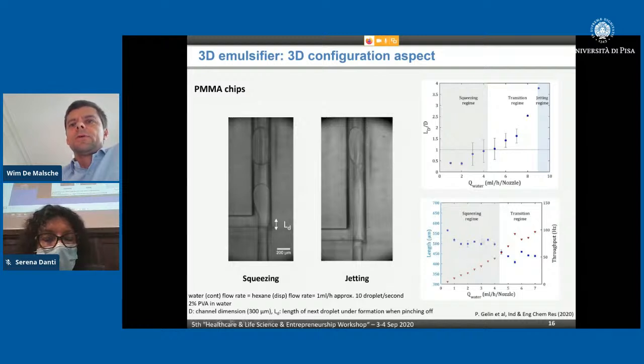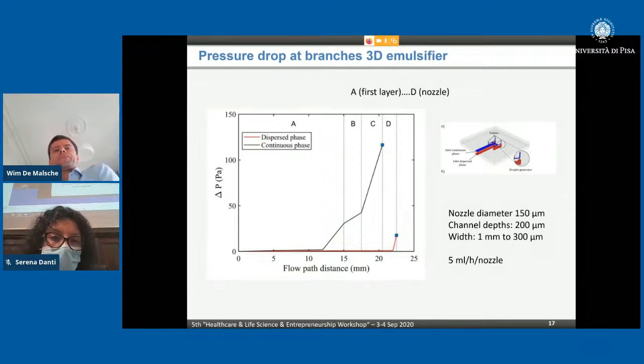And then you can also look at the lengths of these droplets. This gives you a measure of monodispersity. You can see that as we go into the transition regime towards jetting, we start to have bigger fluctuations in terms of size. And here on the right hand, we also see the frequency, which is increasing as we increase the flow rates. All right, and this is a typical image where we have this towards the unstable jetting regime.